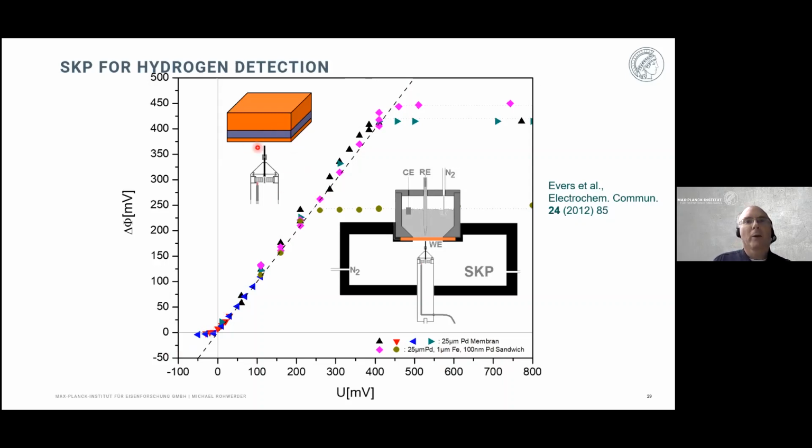And on the surface, again, we see the hydrogen electrode. Now, if we know how the activity of hydrogen, so potential here, is reflected in the amount of hydrogen inside this palladium film that we have evaporated here, then we can use the potential as information for the hydrogen which has entered this palladium layer, this palladium film. It's about 100 nanometer in this case.